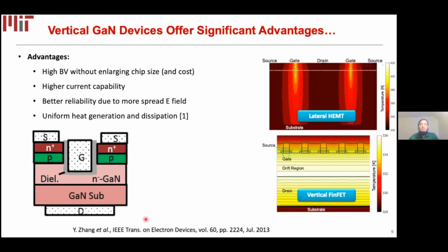For example, if you look at the heat map of vertical versus lateral power devices, as we can see here on the top, in the lateral devices the temperature of the device is very high near the surface, but in vertical devices, temperature is more evenly distributed throughout the substrate. And if you look at this plot, where the x-axis shows the power density versus the temperature of the device, we can see that at the same power density, vertical devices offer much less temperature rise compared to the lateral counterparts. So all these advantages make us really excited to pursue the vertical devices in gallium nitride.